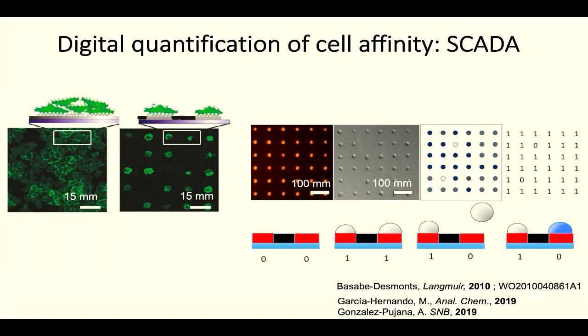And this is exactly true. What you see here is the protein pattern, and what you see here is the bright field optical image of the plate. In this case, these are mesenchymal stem cells adhering to the pattern. So you can immediately relate the number of available dots and the number of occupied dots. So this analogical problem, now we made it digital, and we only need to quantify empty or occupied dots. 1, 0, 1, 0. So it's a very easy and very precise way to quantify the number of cells adhering to a substrate.